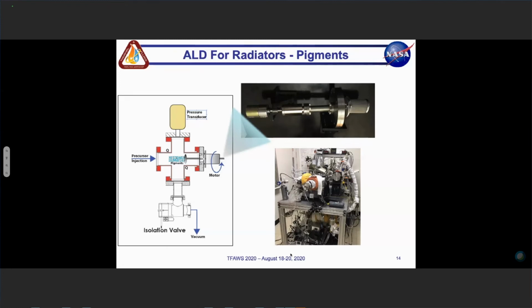So moving on, one thing that we were interested in is that these radiators vary in size, and we want to add some sort of charge dissipating coating on these radiators. Typically what ends up happening is you coat your radiator with your specific thermal coating, then you put it inside of a big oven, and then you put an overcoat of, say, a charge dissipating coating such as indium tin oxide or indium hydroxide. Depending on the size of your radiator, you pretty much need a vacuum system which allows you to put that entire structure inside a chamber, and that can be cost prohibitive. So the idea that we came up with is that instead of coating the entire radiator in the beginning with indium oxide or any of the charge mitigating coatings, we can coat the pigments themselves in the powdered phase before binding onto the radiator, as a way of providing that charge